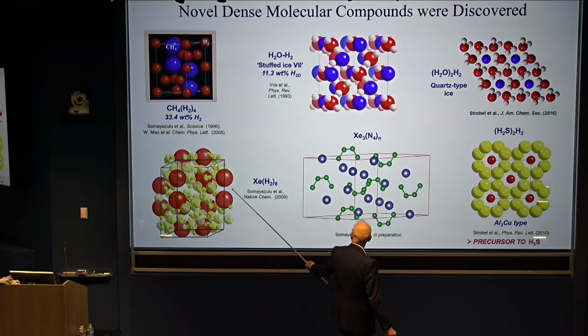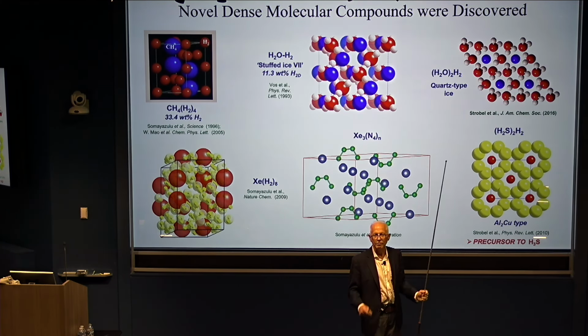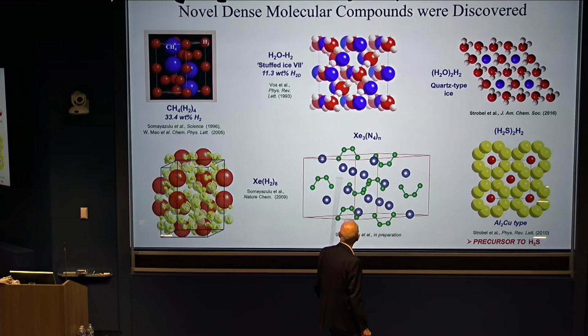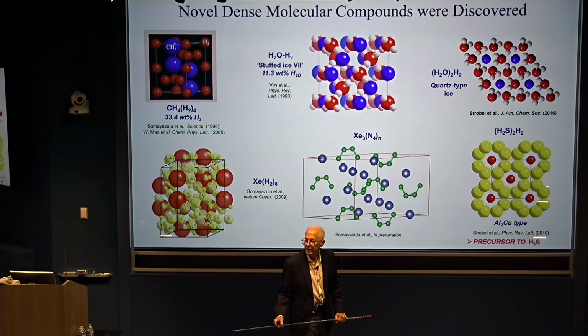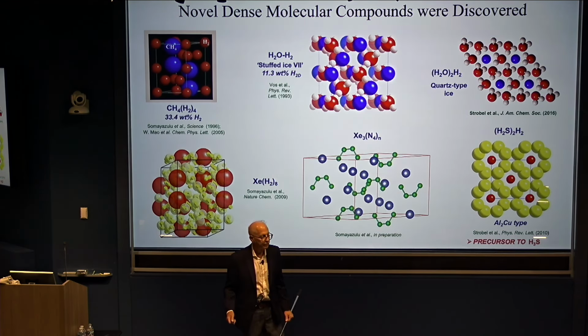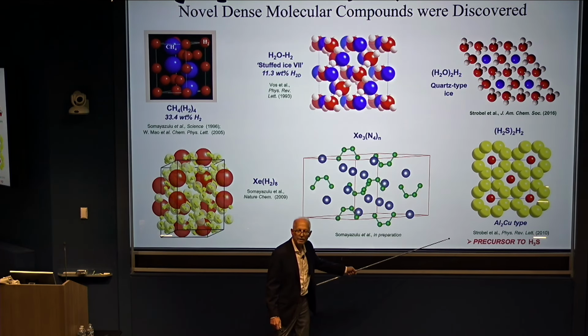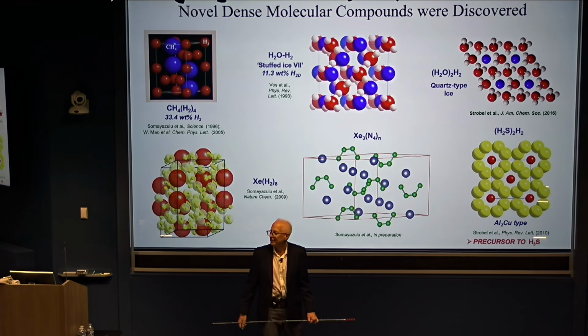This is interesting over here because this is xenon bonding with hydrogen, two things you don't think about forming bonds, but it makes a beautiful structure. This one here was also interesting because it turns out to be the precursor of one of the high temperature superconductors that I'll come to. We simply didn't take it high enough in pressure at that time to see the superconductivity.